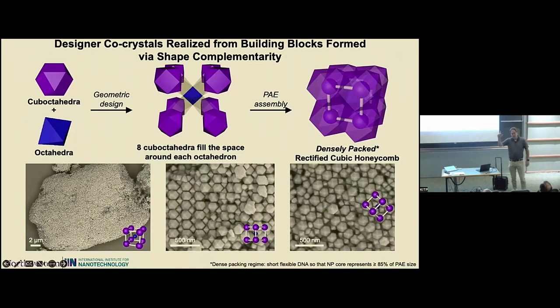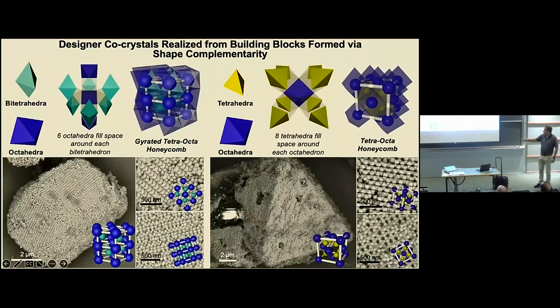But if you use the oligo as a shock absorber, right, that can adjust for the slight differences in particle sizes here, you can get enough of a perfect match to force the formation of these, you know, really exotic types of architectures, the densely packed rectified cubic honeycomb shown here on the right. And then it's not limited to those. So here you can see octahedra and bitetrahedra, and you can see tetrahedra and octahedra. We can now begin to match these to form these really dense architectures where the oligonucleotide is really just a tiny glue that holds each of the architectures together and build these dense-filled systems.